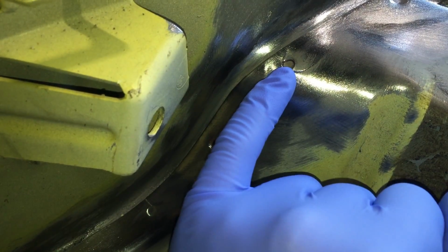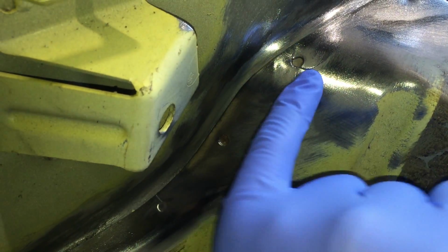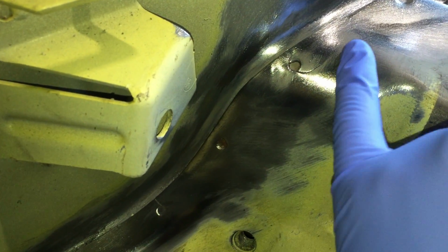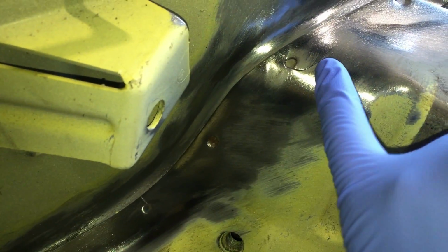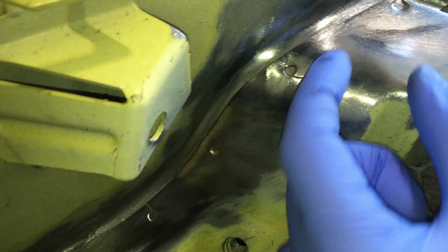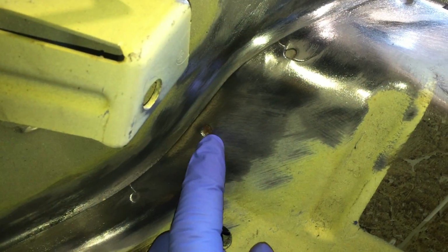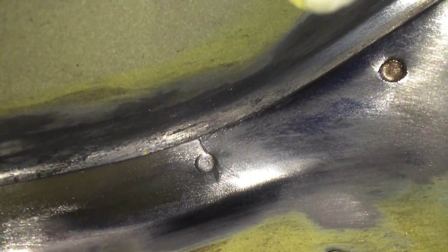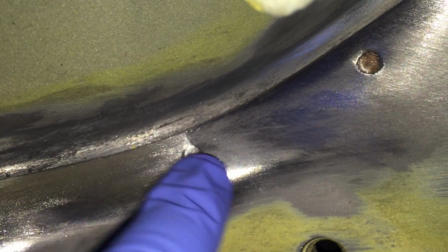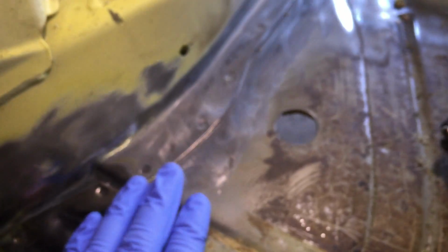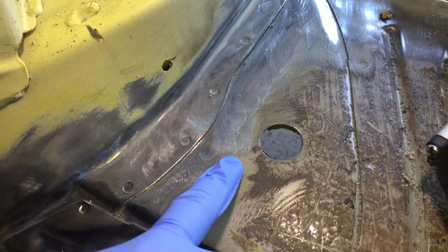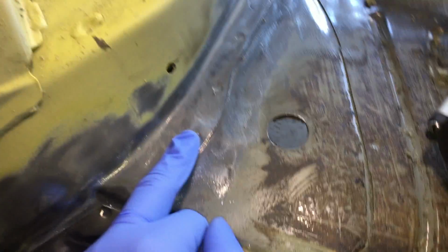So we got a broken spot weld, totally broke there, two cracks going that way, one heading inboard as well into the panel, so we need to find the end of that. I might even continue it and take that section out, because then there's no crack at all. Broken spot weld with corrosion inside that one, and then also another broken spot weld with a crack going around it and two little offshoots inboard. So whilst it's all apart, we're going to stitch weld the rear axle carrier panel to the chassis legs up here.